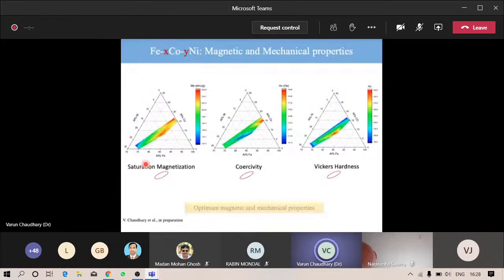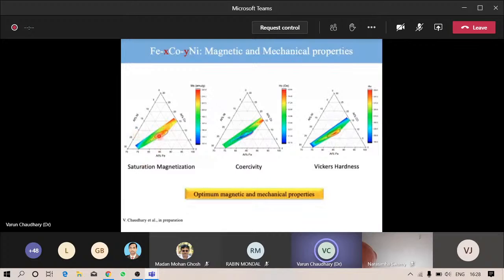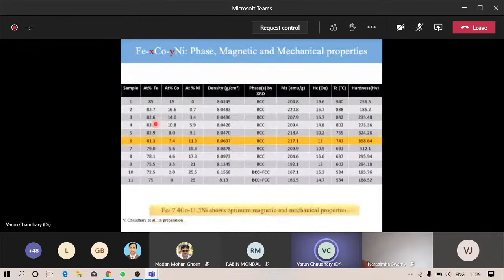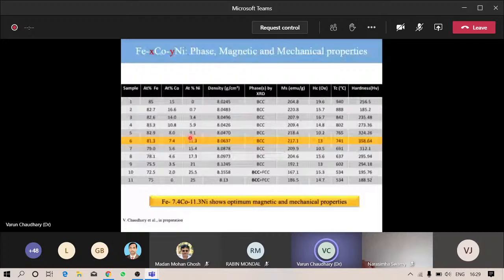I would like to again mention here that we need a material with high saturation magnetization, low coercivity, and high hardness. And we were able to find this space here where we have high saturation magnetization, low coercivity, and high hardness. Currently, we are exploring the other regions of this triangle so that we can find a global optimum space. Here, we tabulated all these results along with the phase, magnetic properties, and Curie temperature. This is the composition which shows optimum magnetic and mechanical properties: iron with 7.4 cobalt and 11.3 nickel.